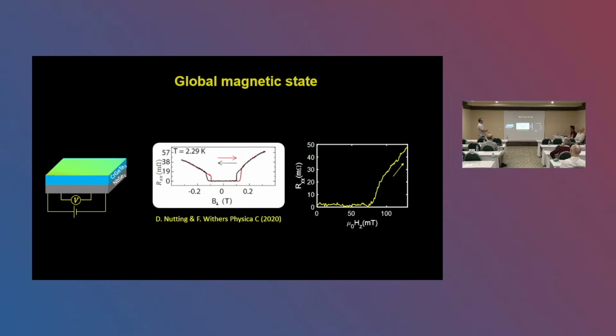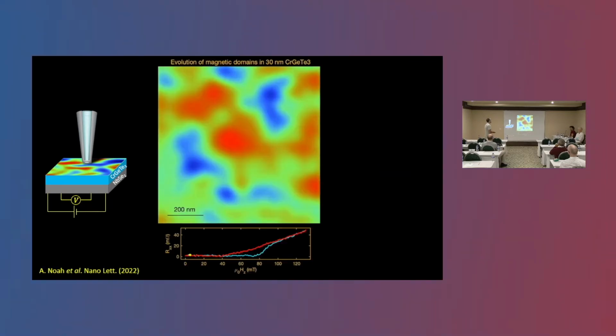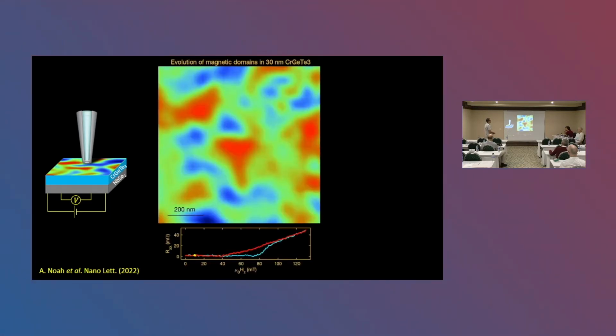So the first thing is we made the same heterostructure in our lab, and we managed to get a similar behavior. But we have the advantage that we can have a look at the same time with our microscope. So what I'm going to show you now is a movie of the magnetic structure evolving, and here you have the transport. Now we're at the zero voltage state, and I'm going to raise the field, and you're going to see what happens.